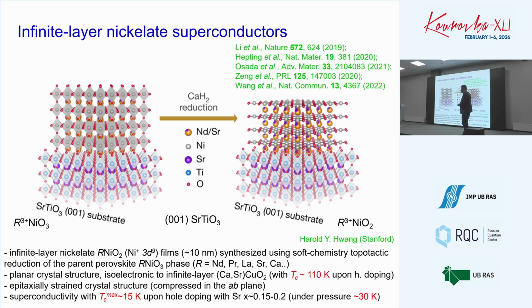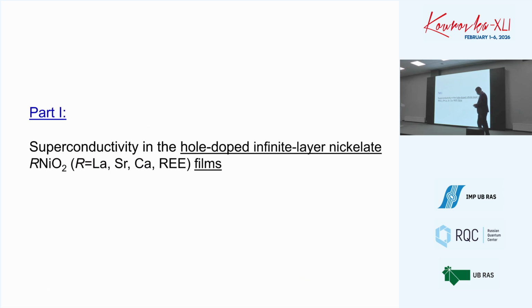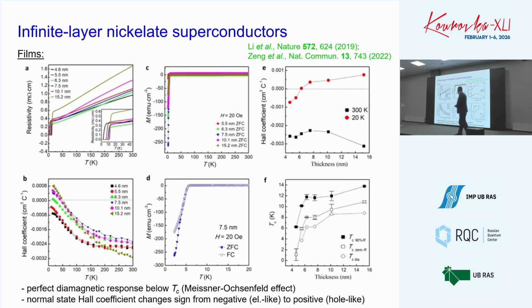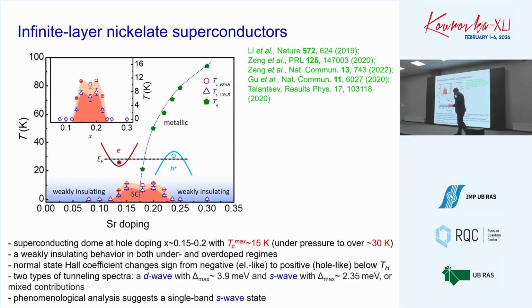People managed to synthesize these infinite-layer nickelates with lanthanum, strontium, and calcium without f elements at all. And they show the same properties. This is absolutely the same superconductivity with Tc about 15 K, the same behavior of the Hall coefficient, which changes sign, and clear evidence of a somewhat anisotropic superconducting dome. Even in tunneling experiments the results were not consistent: some experiments show evidence for d-wave superconductivity, others showed s-wave superconductivity, although some samples showed a mixed s-plus-d state. This is still ongoing research in many respects.